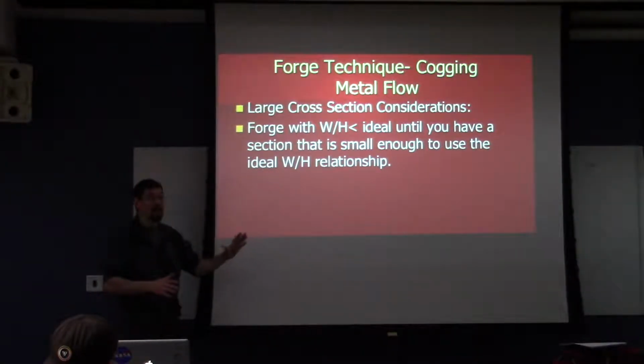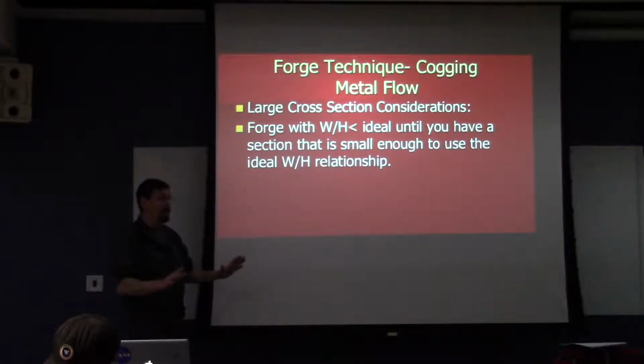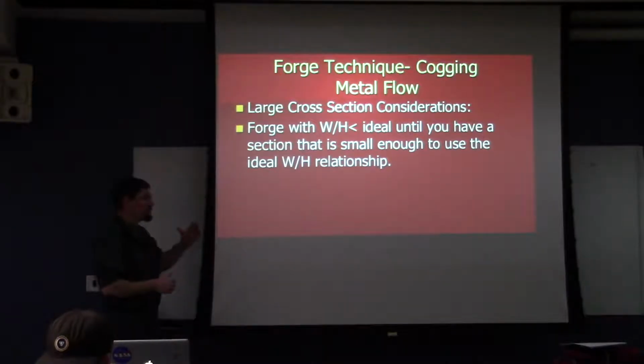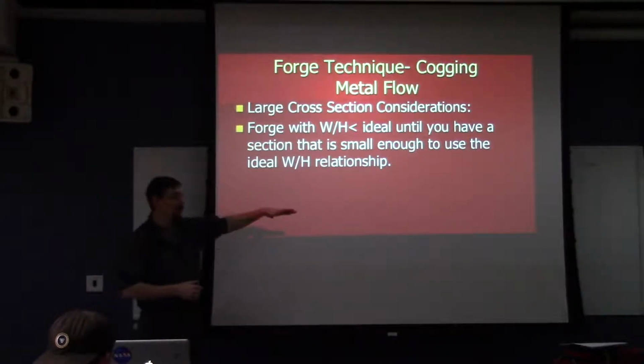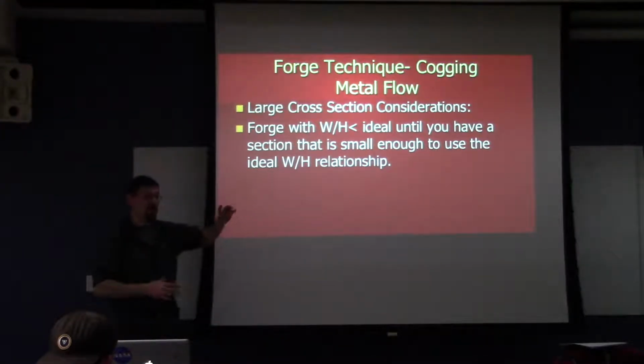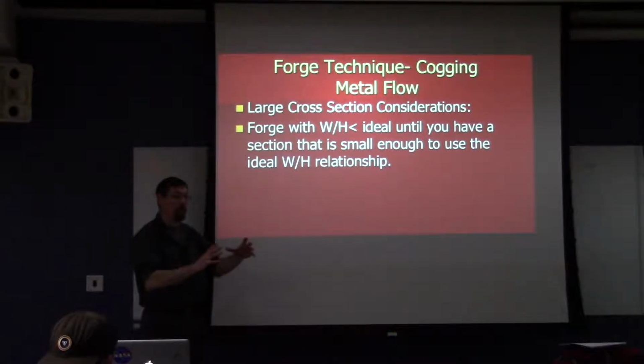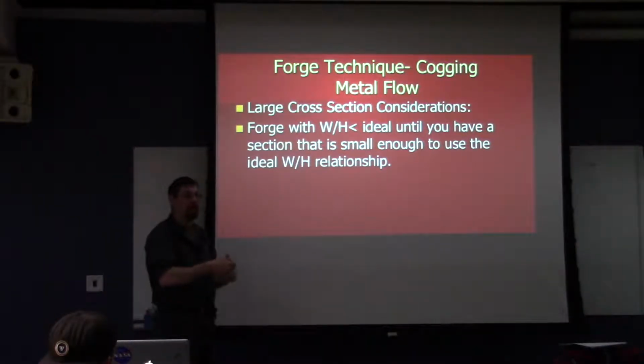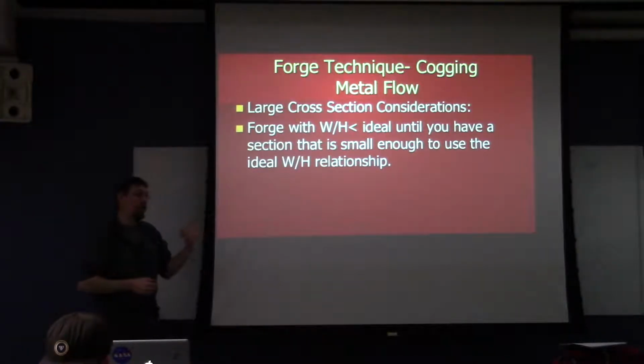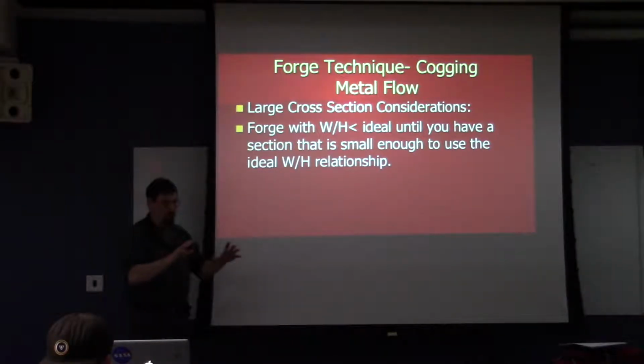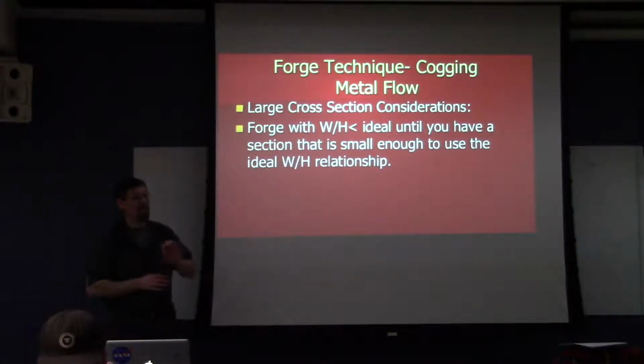And we just recognize that that's going to be the case, and that's okay, as long as we move forward with that understanding. Once we work that piece down to a small enough cross-section that we can get effective reduction, then we can start counting it towards our goal of closing up those holes. So what we would do in practice would be to bring this large cross-section to a press that's really less than ideal. We would forge it, and we have to be very intentional when we stop forging.